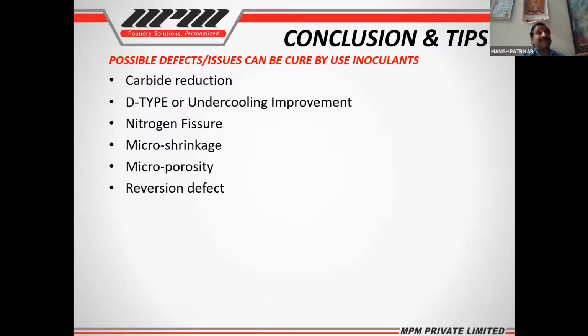defect. The reversion defect is the defect when you have, on the mold, on the casting wall, on the side of the mold, if you are producing SG iron and the flakes are coming in the SG iron on the wall of the casting which is facing the mold, then that is called the reversion defect. It is possible to reduce it by using cerium based inoculants.